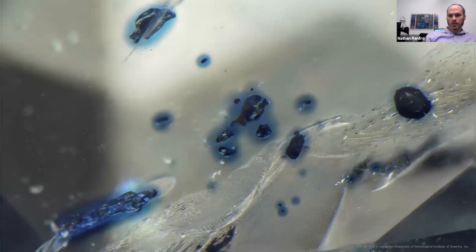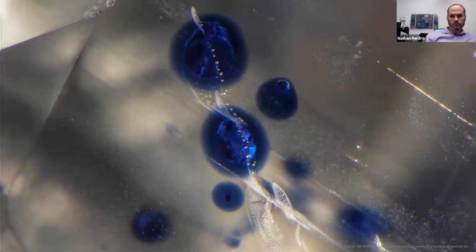So we're basically just redistributing the chemistry of that sapphire to modify the color — and that's how we get Montana sapphires that instead of being a sort of coke-bottle green color, can now be a vibrant blue. With proto-genetic rutiles you have these really significant blue halos with a kind of ink-spot look. When you have a lot of these proto-genetic rutiles, you can get kind of an uneven spotty color, which may not be quite as desirable as when you have internal diffusion around rutile silk, which tends to give a more uniform distribution of blue color.